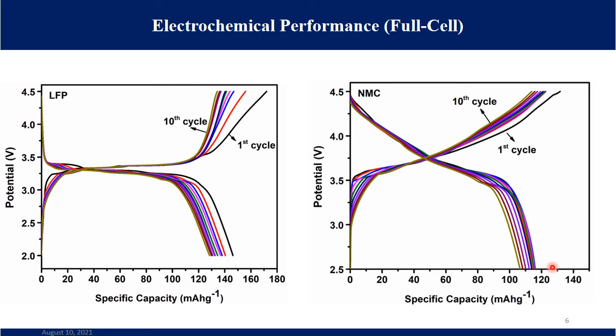However, the electrochemical performance of the pencil lead full cells may mainly depend on the counter cathode materials. The energy densities of the fabricated cells are also found to be 155 watt hour per kg and 141 watt hour per kg for LFP and NMC cathodes respectively.